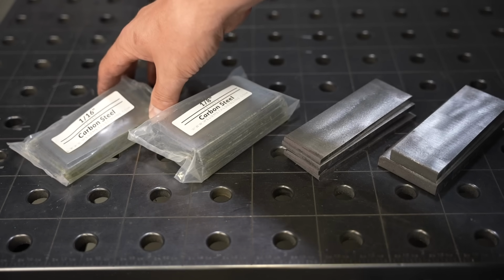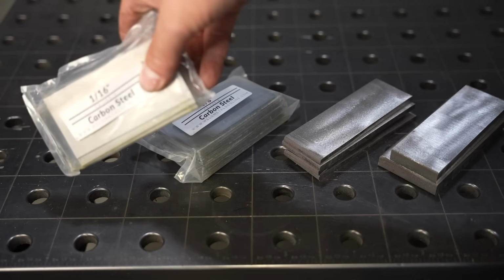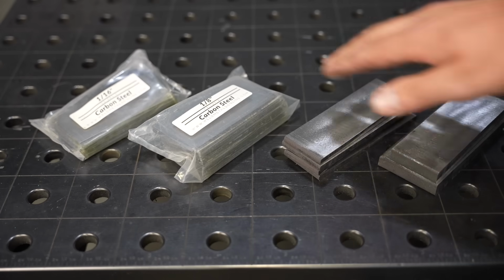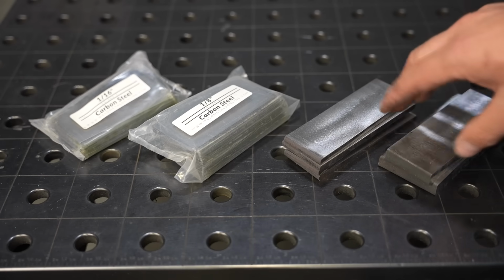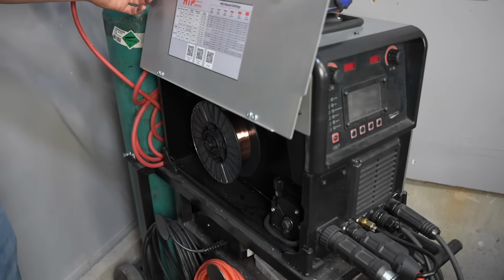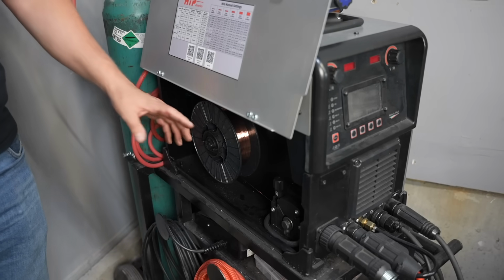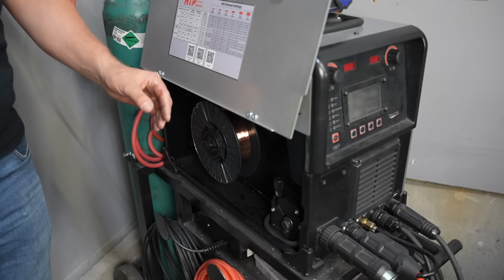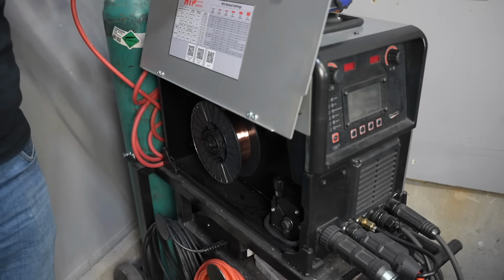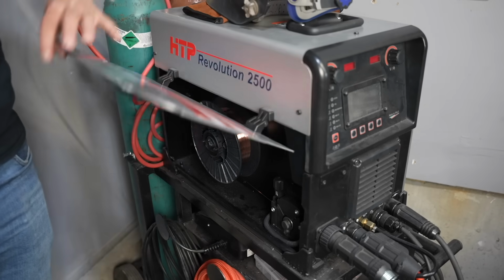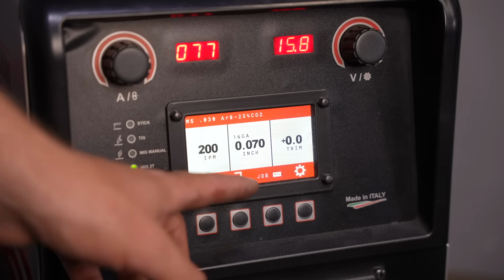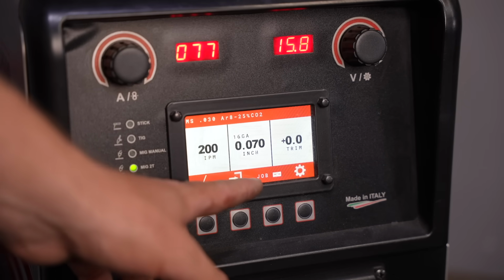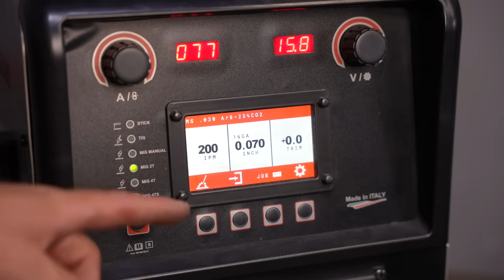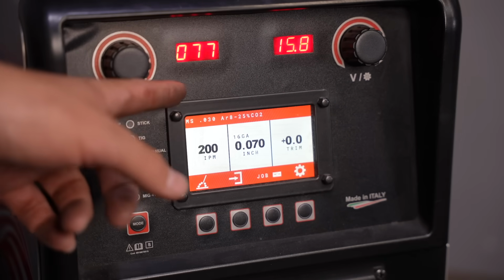So I have some coupons here ranging from 1/16th of an inch clear up to 1/2 inch thick plate. I have .030 wire loaded in here, which is really good. I use it a lot for 16 gauge square tubing, which is what I use for a lot of things. 200 inches per minute is going to be good for 16 gauge. It already has the voltage set for me and it'll give me right around 77 amps.